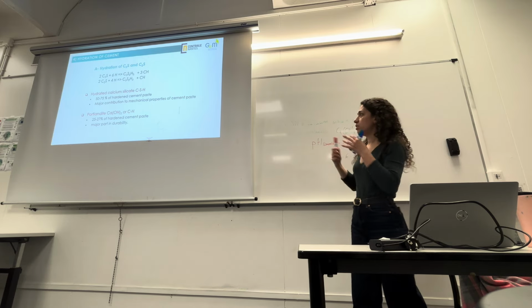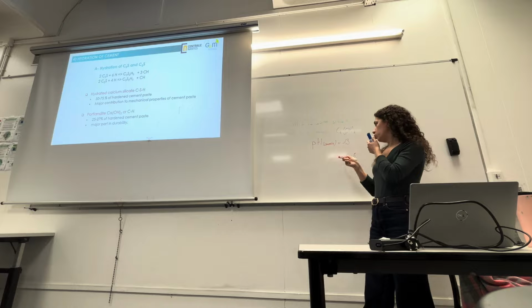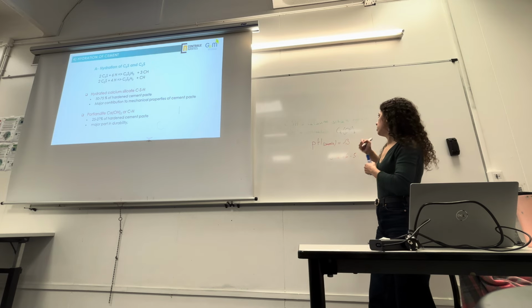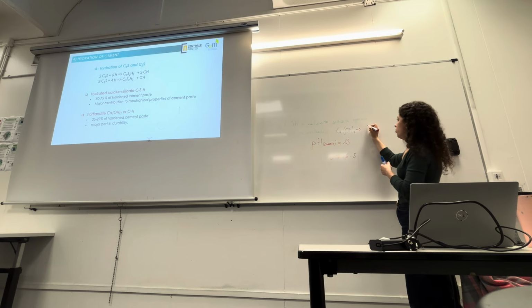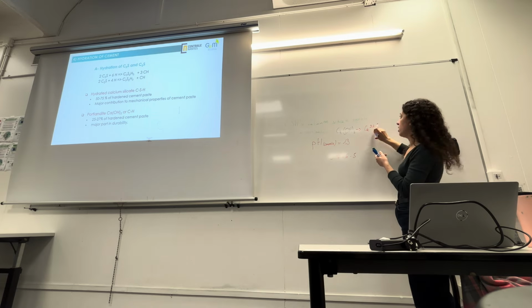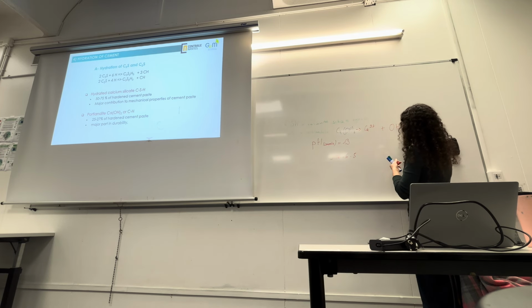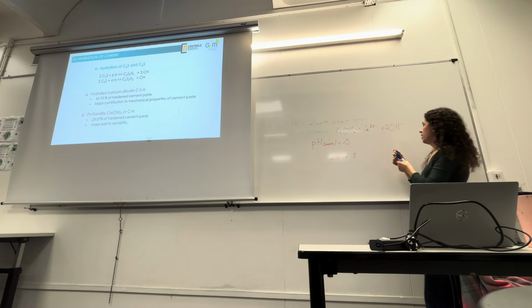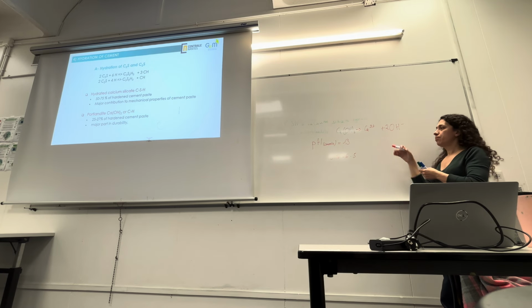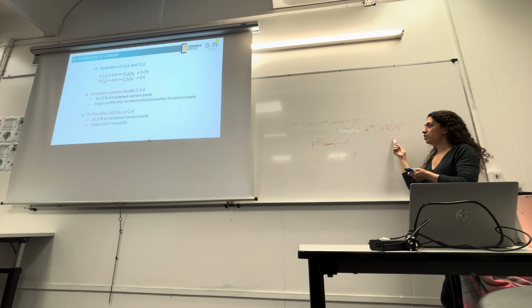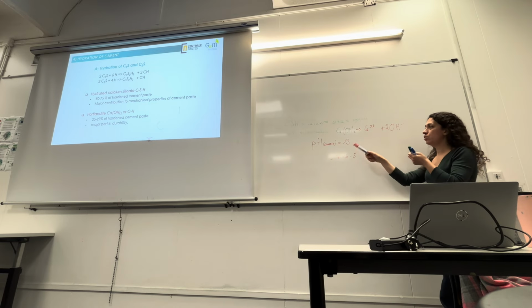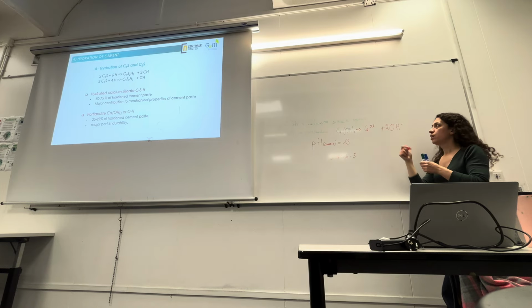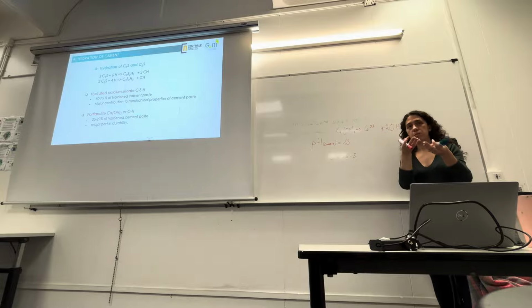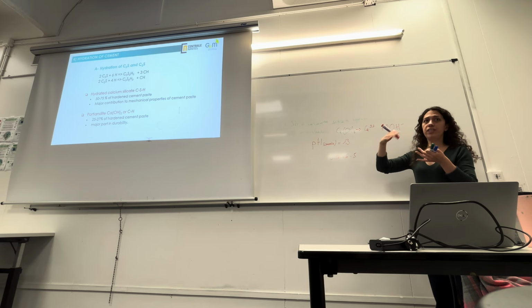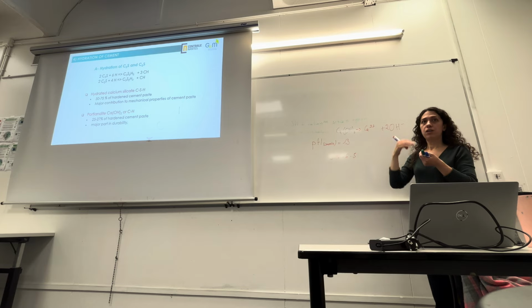And what is the defense mechanism of the cement paste against water aggression? It's the dissolution of Portlandite. Because if Portlandite dissolves, we get calcium released, and also two hydroxide ions released. And these ions increase the pH. And so the concrete will reach again a pH around 13. So if you put concrete or a cement paste sample inside a tank of water, the Portlandite will continuously dissolve until it reaches again a pH of 13.